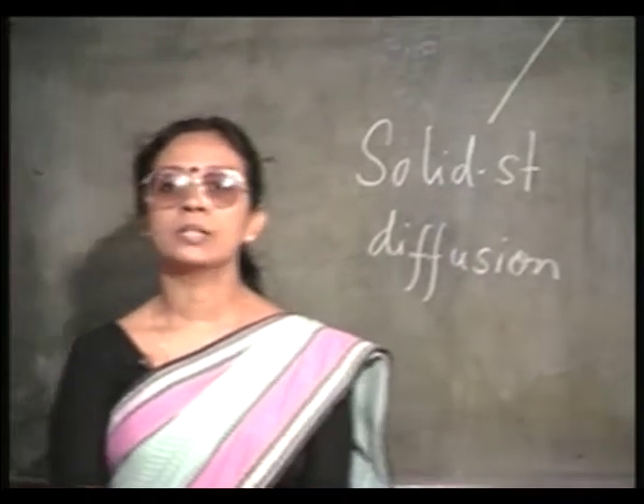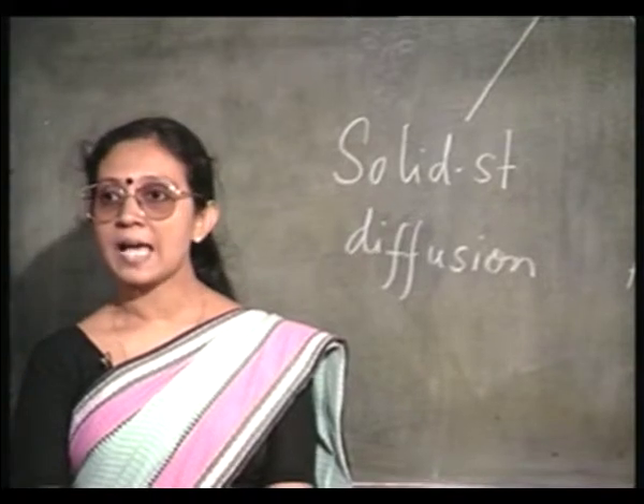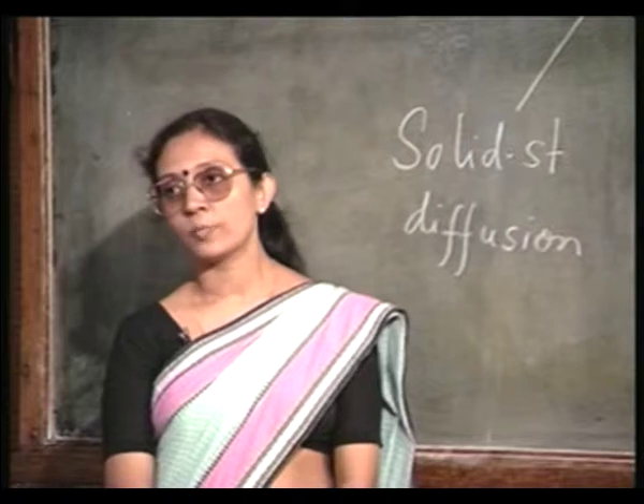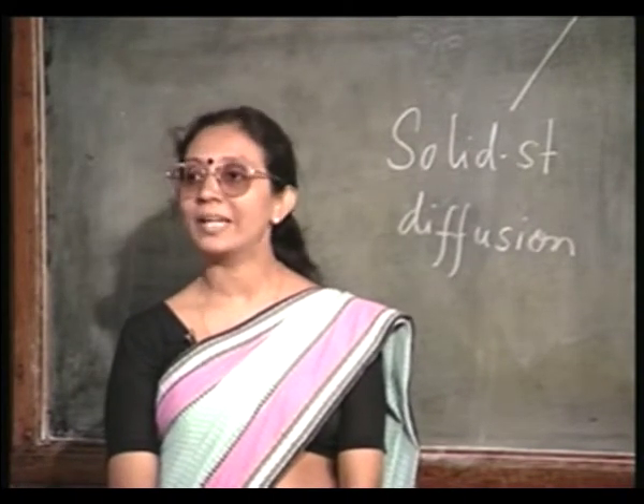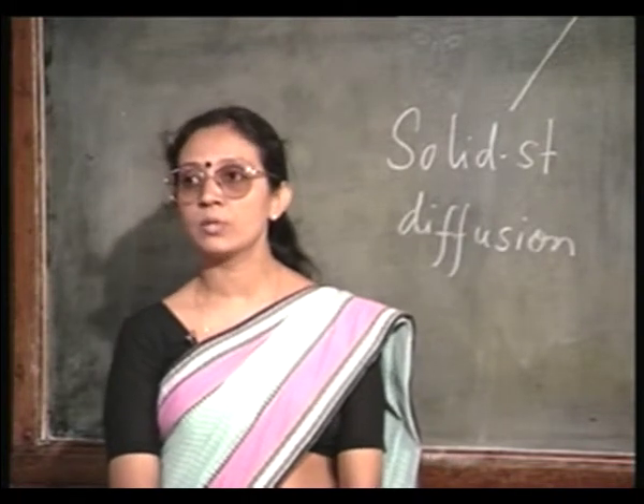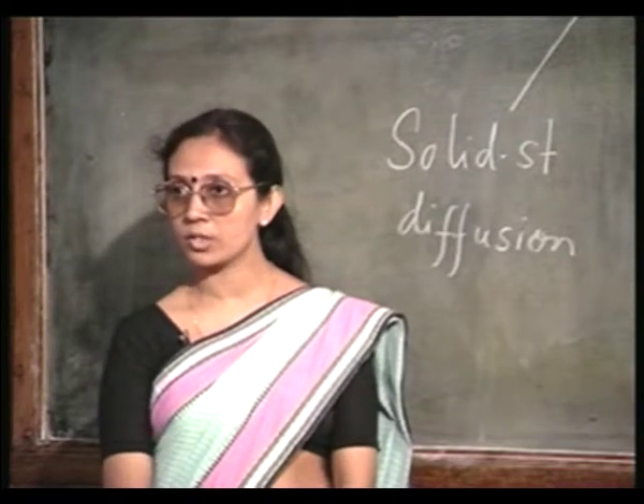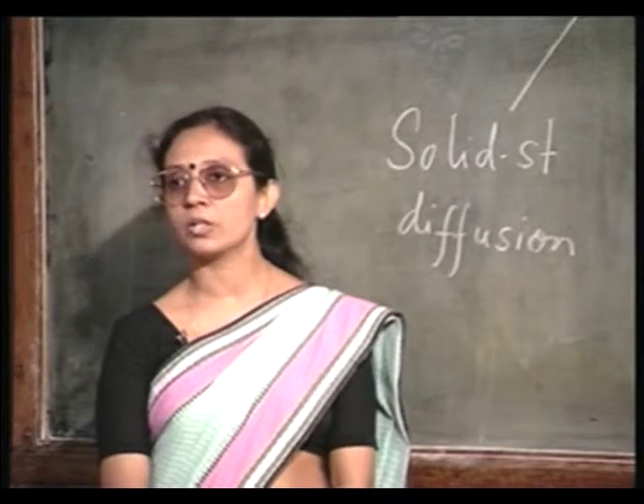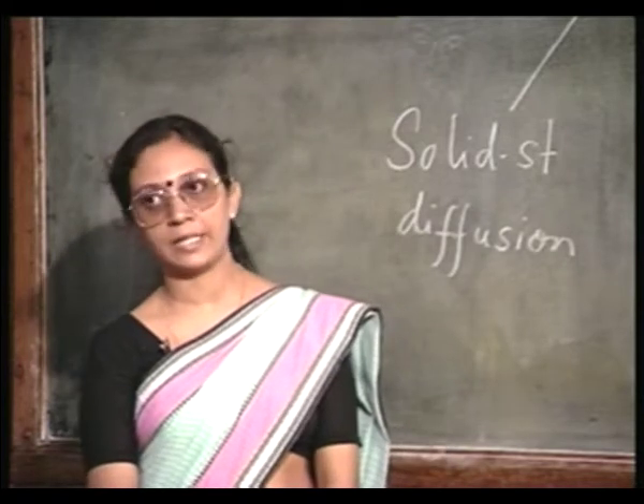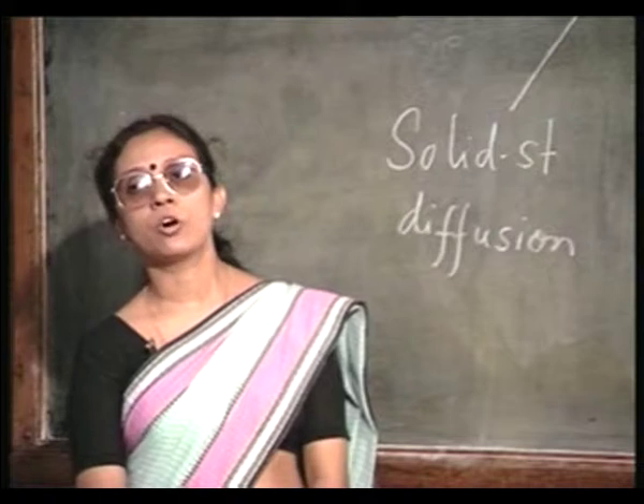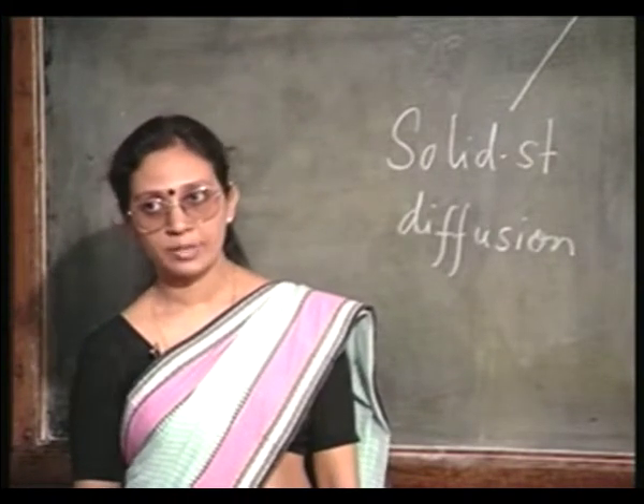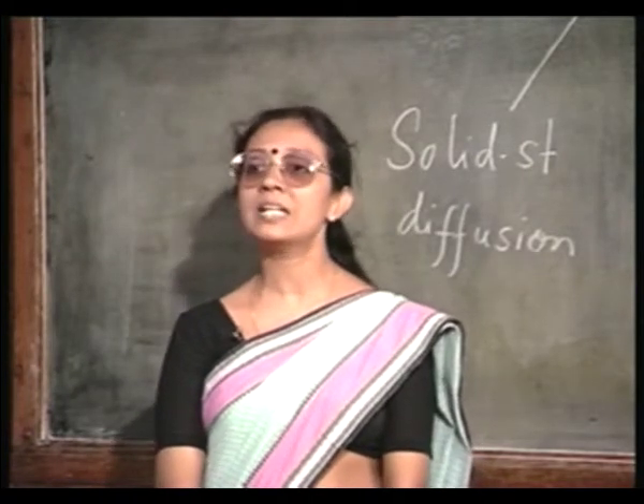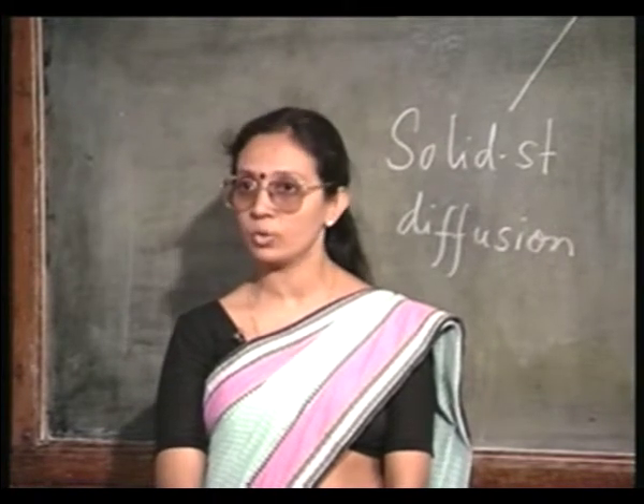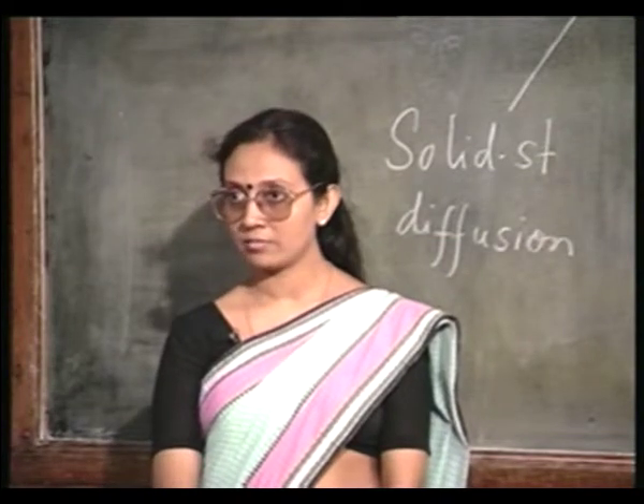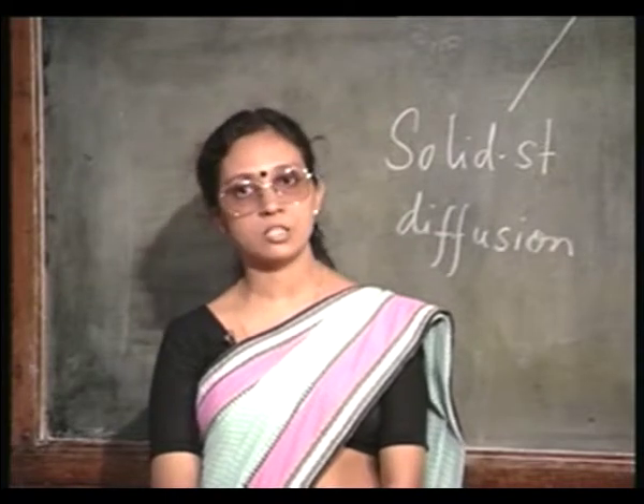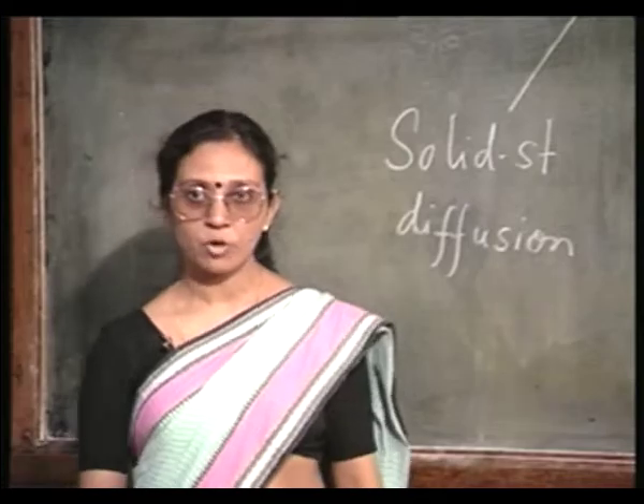The other thing is of course solid state diffusion. That is, as the epitaxial layer is being grown, if the doping concentrations of the substrate and the epitaxial layer are widely different, as in most cases it is likely to be, then there will be a diffusion from the higher concentration side to the lower concentration side, and that will also modulate the deliberate doping concentration of your epitaxial layer. So, both these effects will cause a change in the doping concentration of the epitaxial layer, and therefore, it will put a limit to how thin a layer you can grow with proper control of doping, because you understand there is going to be a transition layer between the bulk and the epitaxial layer. There is going to be a transition layer which will be determined by these effects of auto doping.